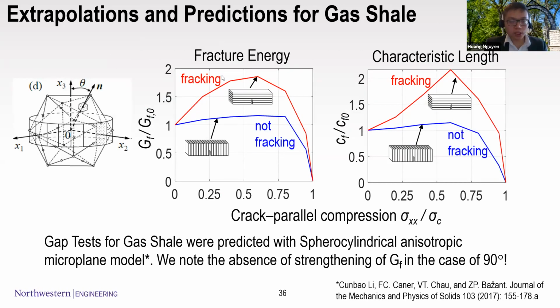And another extrapolation we have done is for shale. For the fracture energy of shale, in the case that you have the bedding plane perpendicular to the crack, it follows strictly the trend in the concrete. However, when you have the bedding plane parallel to the crack, because you have the weaker plane that is already aligned with the crack, it is very sensitive to the splitting, the strengthening regime is very limited, and you can see that it's more sensitive to the sigma xx. However, it's not usually the case in fracking, because in fracking you have the crack that expands perpendicular to whatever the bedding plane is, based on the natural stress state of the rock.